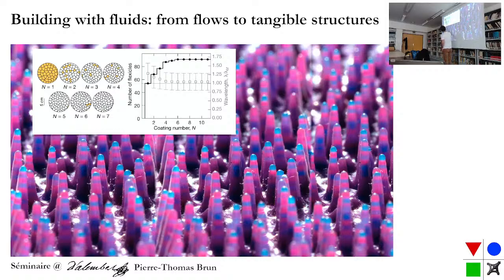So initially, you have your drops here for one coating, so this sort of irregular distribution of drops. And in yellow, we color new drops. So initially, we were here, n equal 1. And so you see that you don't have that many drops compared to what you're supposed to have, which is this prediction from the stability analysis. And conversely, the wavelength is quite high. So we're almost at 1.25 compared to the one we were supposed to have.